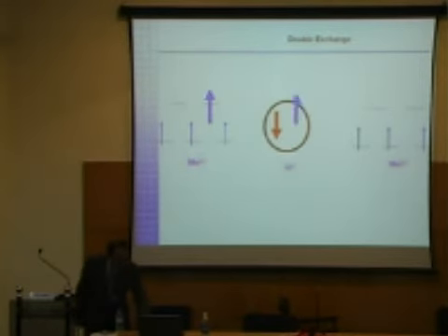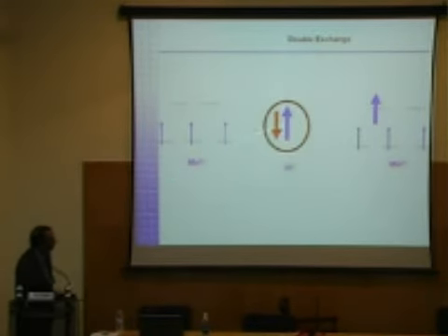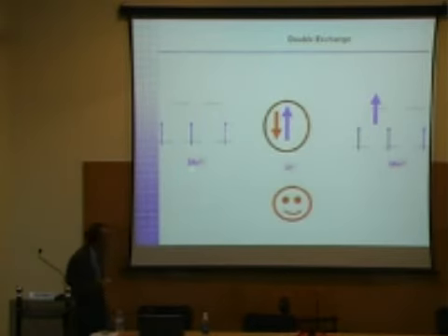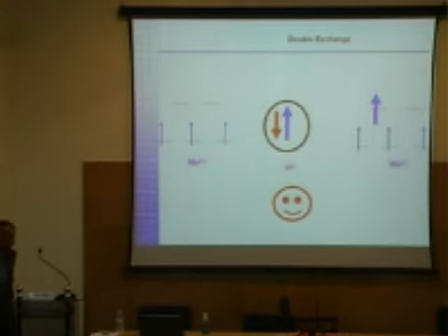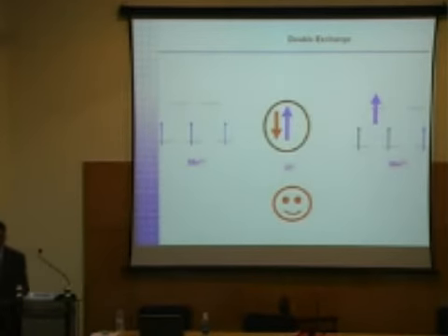So let's watch this. Okay, all right. So that electron goes there. And as you can see now, this is a good arrangement here. So what does it tell you? The spin alignment of manganese 3+ and 4+, if I have 2 of them next to each other, is supposed to be ferromagnetic. In fact, the research in the last 10 years has been extensively on this work to see if I can somehow increase the transport properties by applying magnetic fields. That led to the big area of magnetoresistive materials, which are also used in computers.